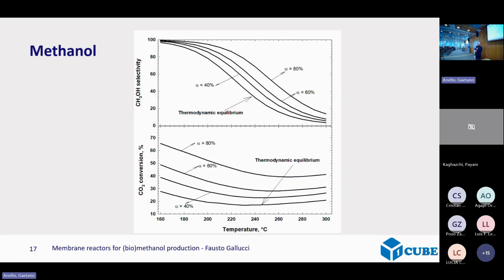Now, if you take a membrane and you start removing water, these are simulation results. Already removing 30 to 40% of the water, you have a much better conversion if you fix the pressure, of course. And if you would be able to remove a lot of water, then the conversion increases quite a lot, which means also that in principle, you could have the same conversion per pass, but working at much lower pressure. Which, if you are working with hydrogen, is very nice because it's easy to get hydrogen from an electrolyzer at 30 bar. It's more complicated to go to 100 bar or 120 bar, the typical pressure where the methanol is produced.